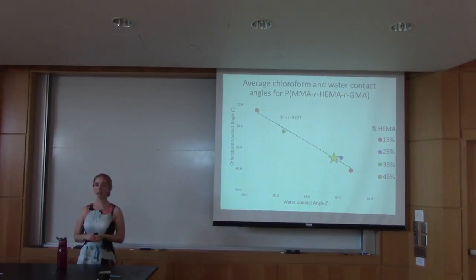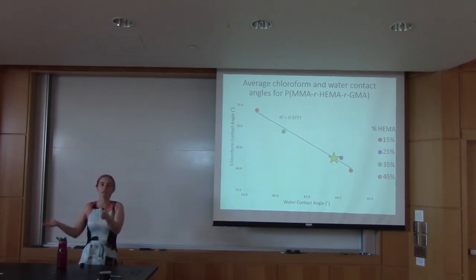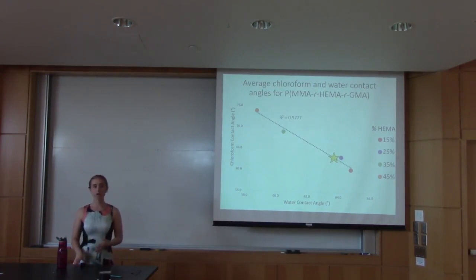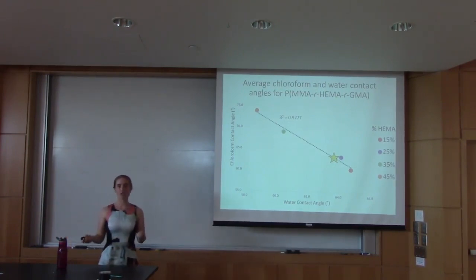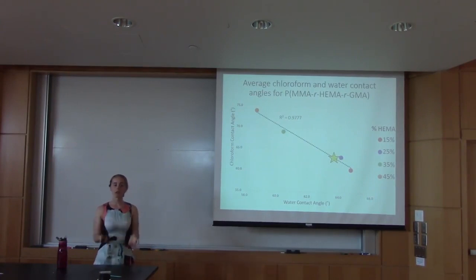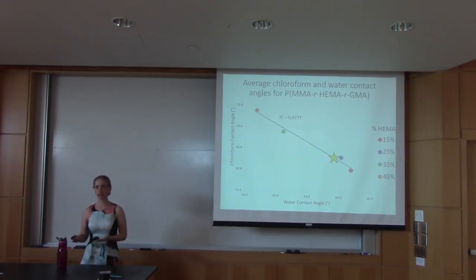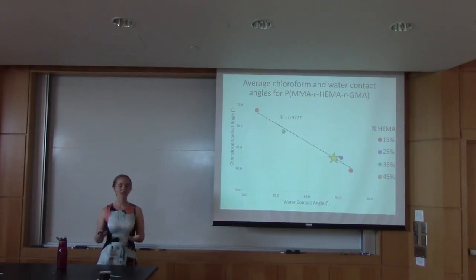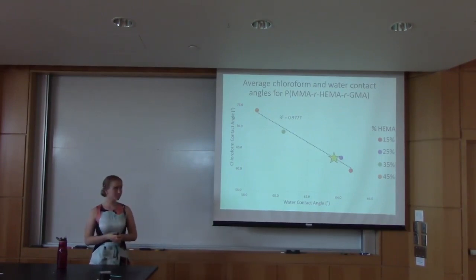It's not exactly that, and part of the reason why it might not exactly lie on that trend line is because when we make these random copolymers, they're self-assembling. So instead of us manually putting together each of these units of the polymer, it's self-assembling. And so we only have so much control over how much is going to be in each individual strand percentage-wise. So while we may put in 25% HEMA, we might actually get out 24% HEMA or 23% HEMA, and that can alter our surface energy, that can alter how hydrophilic or hydrophobic it is.